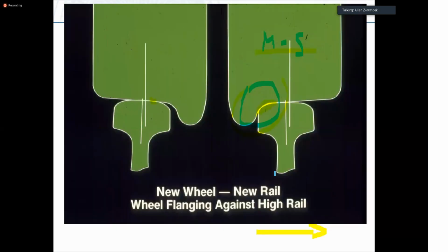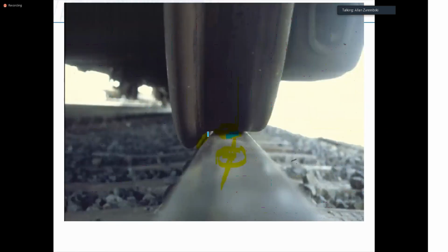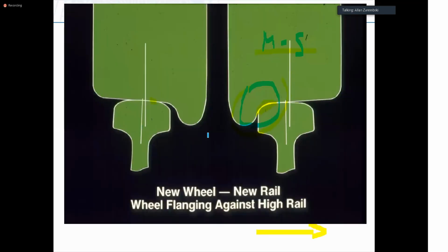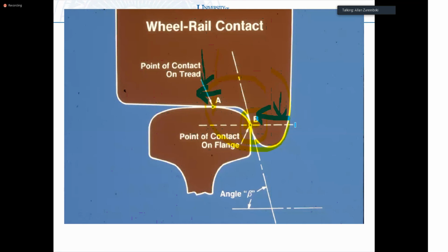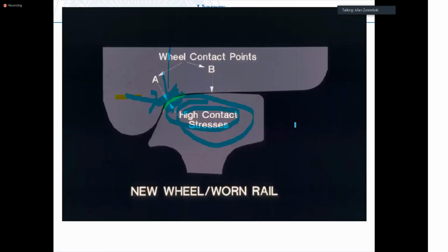On shallow curves, where you can use the conicity of the wheel set to steer around the curves, you should still be able to maintain this gap and have the center contact. But once you get to medium to sharp curves, you start to flange. And once you start to flange, you have two-point contact. So your choice is two-point contact versus one-point contact. And the answer as to which is better is: it depends. This is a case where you really have to match your contact with your loading condition.